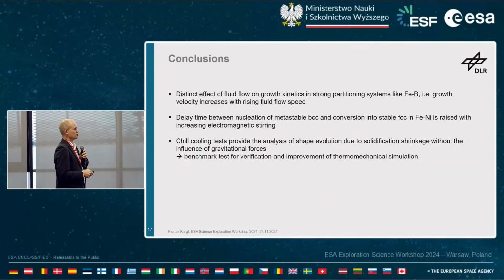So conclusions of this first part of the 3 projects. So we have seen distinct effect of the fluid flow and growth kinetics in the strong partitioning systems like iron boron. So growth velocity increases with rising fluid flow speed. We have seen that the delay time between the nucleation of metastable and stable phase is raised with increasing electromagnetic stirring, and the chill cooling tests provide analysis of shape evolution due to the solidification shrinkage without the influence of gravitational forces, and this serves as a benchmark test for verification and improvement of these thermomechanical simulations.